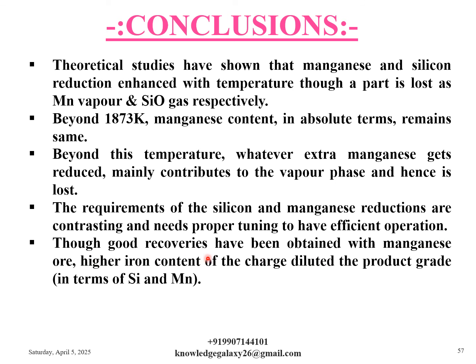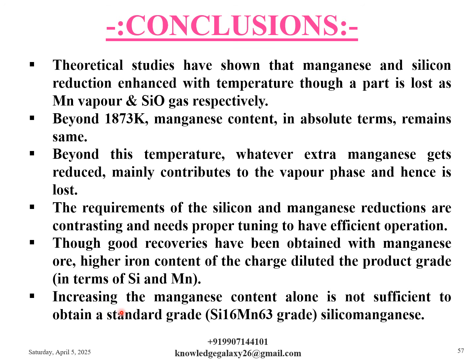Though good recoveries have been obtained with manganese ore, higher iron content of the charge diluted the product grade in terms of silicon and manganese. Increasing the manganese content alone is not sufficient to obtain a standard grade, that is of silicon 16, manganese 63 grade silicomanganese. So these are the main conclusions of whatever observations and experiments I have explained.